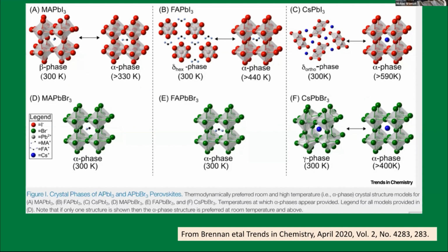And so just so you understand, if you look at the iodide series, the lead iodide series, there is cesium, but you have to go over 590 Kelvin, okay? That's over 300 Celsius to get the desired alpha phase. This is a cubic phase. And for formamidinium, it's 163 degrees Celsius. So you have to be up there, then you get that phase. But at room temperature, it converts spontaneously to the yellow phase, which is useless. It doesn't have any light absorption, and you can't use it in photovoltaics.